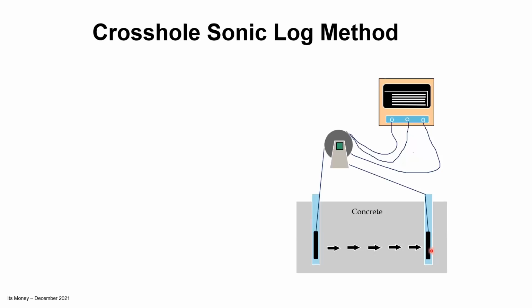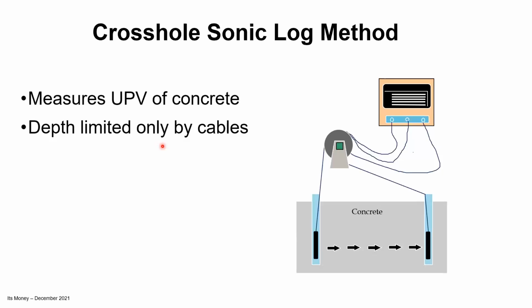The test is repeated at discrete intervals as the transducers are raised up the shaft, so we can build up a vertical profile of the transmission time through the concrete, which is a direct function of the concrete quality. Measuring the ultrasonic pulse velocity of the concrete, which is a function of the modulus and density of the material. The depth is limited only by the cables that you can lower down the hole.